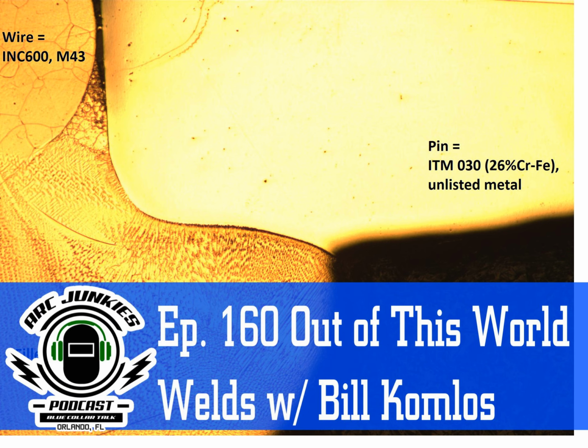Well, they clad it with Inconel, an Inconel 601, I think it was. It's aluminum bearing Inconel. But it's 60% nickel, and you couldn't have that touching the magnesium because magnesium just eats it alive. But once these long seams would blow out, well, then the cladding was gone. One of them is on my website, arctechllc.com. We poured in 300 pounds of Inconel filler metal 82 at $35 a pound into this crucible to repair the long seam and reclad it. And it only lasted 9 months. And I'm going, oh gosh, I'm never going to get another job from these guys. And son of a gun, I'm still working for them 10 years later, so I must have been okay.